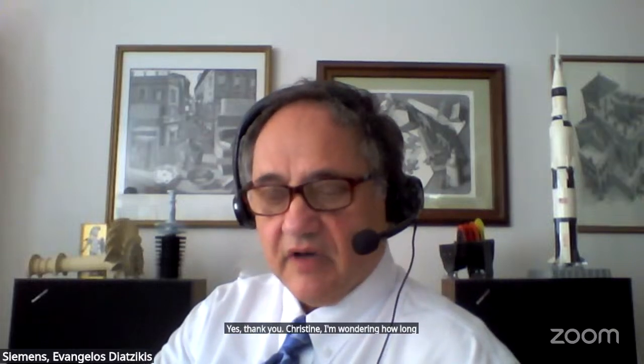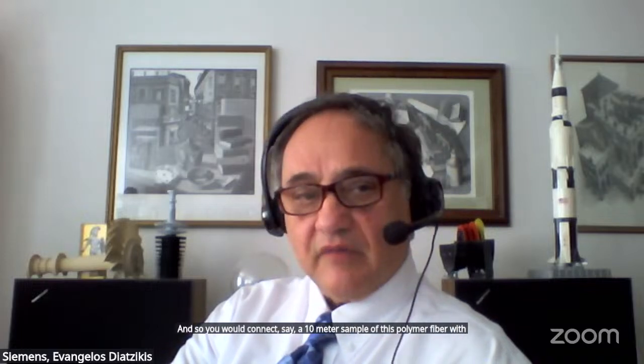Evangelos. Yes, thank you. Christian, I'm wondering, how long can you manufacture these fibers in length? Well, the manufacturing length is given by the size of the preform. We can make manufacturing runs of a few hundred meters to a few kilometers. But the application of these fibers is limited by the loss of the fibers. So the polymers have loss, but the microstructure might also be a little bit scattering. So for most applications, we're looking at a maximum length of 10 meters. And so you would connect, say, a 10-meter sample of this polymer fiber with other fibers in order to carry the signal, say, to the analyzer? Yes, definitely one kind of architecture that we could use. We also have our contrast system where we've tried the approach of saying instead of having a backbone of glass fibers, you would just make the interrogator cheap enough and with radio transmitters, so you can just distribute them in that sense instead. Thank you.